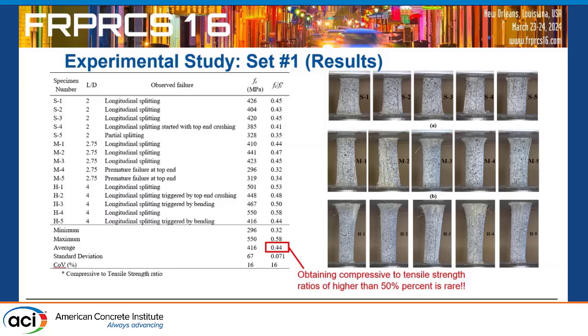You see the compressive strength in MPa and the compressive strength over the tensile strength reported by the manufacturer. And these are the ratios. You see the average is around 44% of tensile strength. And the failure was obvious, initiated at the ends. And that's what we expected. But we wanted to show that this test method doesn't work. But even this one, at 44%, it's not 0.